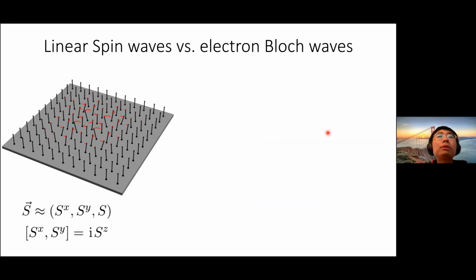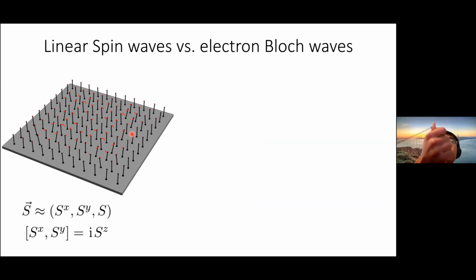Think about a ferromagnet where spin is pointing in a certain direction. In this specific case, let's think about spin polarized along the z direction. If spin is almost polarized around z direction, it can really only vary around that. So the small fluctuation of spin is really the x and y component, because the z component is almost polarized in the system. So in this case, the low energy variable describing the dynamics of the system is really the xy component.